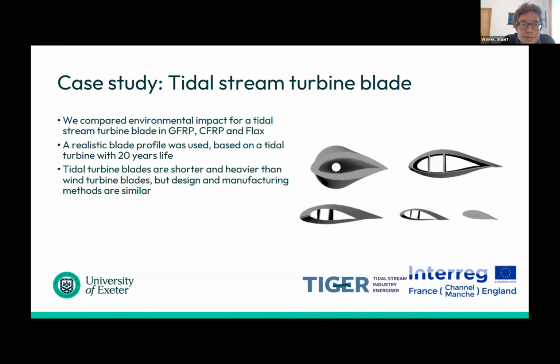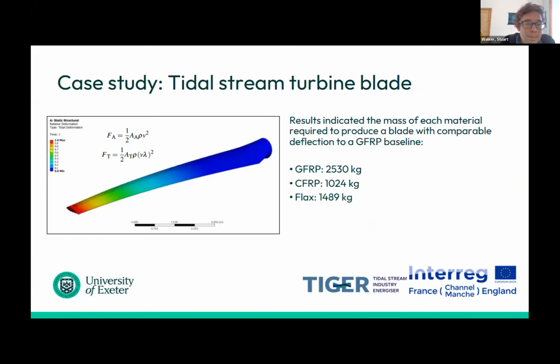So the first step we did was to work out what mass of material you would need to have comparative performance to a glass fiber blade. You can see there we end up with a glass fiber blade about 2.5 tons, a carbon fiber blade of about a ton, and a flax blade about 1.5 tons. So that looks quite good for the flax in theory. It's not as heavy as the glass fiber needs to be, so that's an advantage.